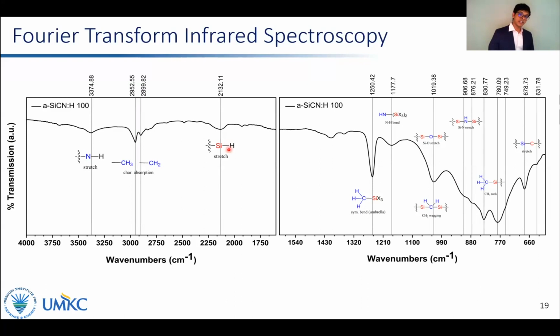SiH stretch was unique, not present in the HMDS precursor, along with SiCH3 wag. At elevated temperatures during our deposition, the CH stretch region and the fingerprint region of the spectrum became diffuse and featureless, indicating that the films underwent significant cross-linking or ceramization. A detailed analysis of the variation of the structures is presented in the dissertation.